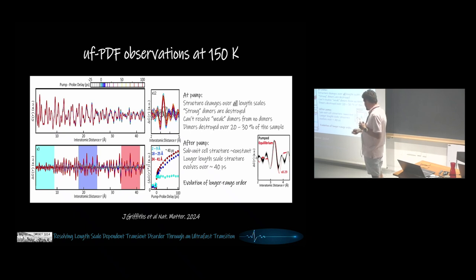And so what you see is that for this short-range structure, you just observe a jump. There is no structure to it because we did not have data in the sub-picosecond regime. So anything that has happened to the local structure happened in basically the femtosecond regime, which agrees with, for example, vanadium dioxide, where you melt the dimer order on the time scale of 100 femtoseconds, I think. Whereas, if you look at those blue and red boxes that correspond to the longer length scales, you see a jump followed by a much slower relaxation, which is of the order of a 40 picosecond time constant. So the longer length scale structure evolves further, whereas the local structure does not.